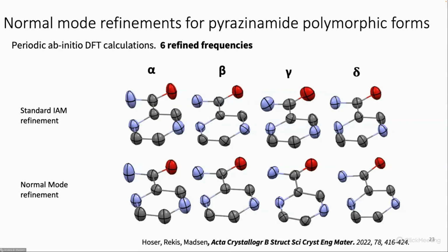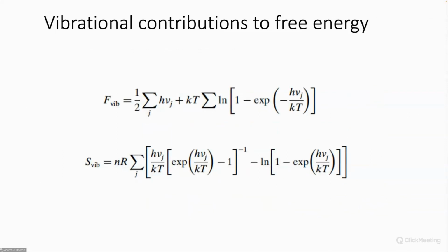And here, in the normal mode refinement, we have only refined 6 parameters. So instead of all the anisotropic displacement parameters that we normally refine for each individual atom, we only refine 6 frequencies. We are using much fewer parameters and getting almost the same fit, a slightly higher R value than we would get for the independent atom model. With those frequencies in hand, we can derive the vibrational contribution to the free energy from these normal modes, not only from the modes that we have refined, but also from the remaining modes that are retained from the quantum mechanical calculation. So we have a range of frequencies that we can then use to derive the vibrational enthalpy and the vibrational entropy using these equations here.